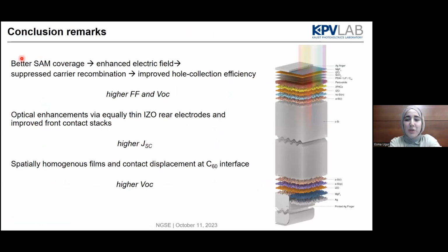And with this, I want to conclude. With the better self-assembly monolayer coverage at the HTL interface, it's enhancing the electric field, therefore it is improving the hole collection efficiency. Therefore, we have a higher fill factor and open circuit voltage. And from the optical enhancement with the thin IZO at the top and also the rear side, we can get higher JSC. And also with the homogeneous perovskite films, and for sure, dealing with the C60 interface, it's also enhancing the open circuit voltage of these devices.